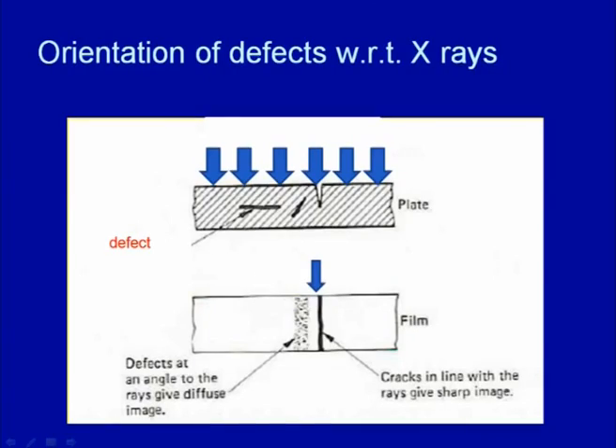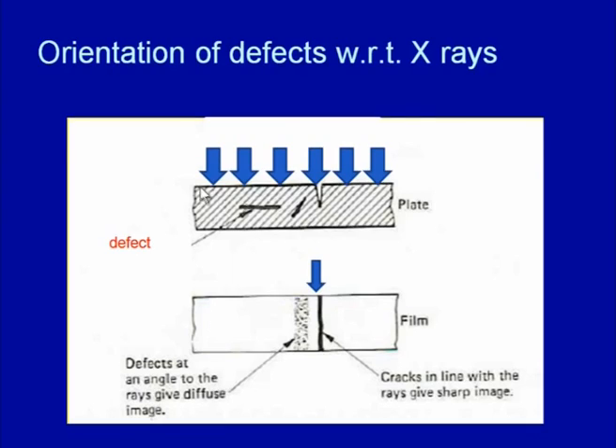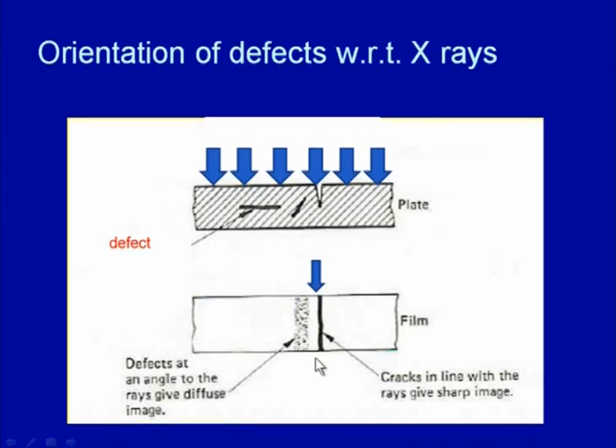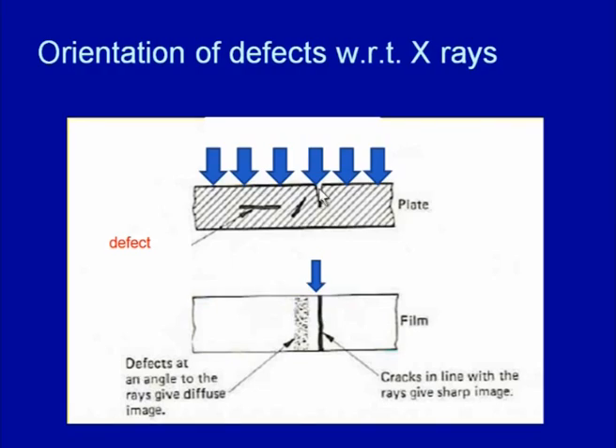This typical schematic diagram shows that X-rays are being supplied from the top. At locations where we do not have any defect, the rays will be absorbed to a greater extent and less will reach the other side where the film is placed. But wherever we have a defect, defects are of low density material, so the rays will be absorbed less and more radiation will reach the other side and affect the film to a greater extent, darkening it more. Wherever more darkening has taken place, that shows the greater presence or larger size of the defect. We can take radiographs in two different directions in order to locate exactly where the defect is present.